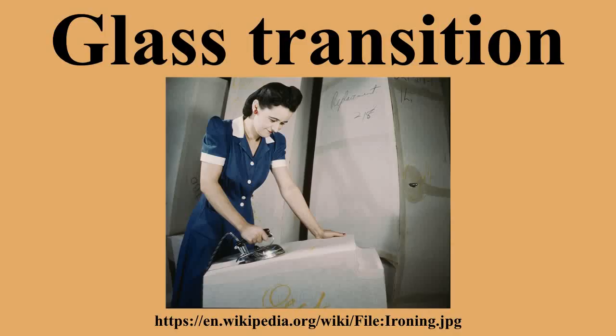The formation of a non-crystalline form of a gold-silicon alloy by the method of splat quenching from the melt led to further considerations of the influence of electronic structure on glass forming ability, based on the properties of the metallic bond. Other work indicates that the mobility of localized electrons is enhanced by the presence of dynamic phonon modes.